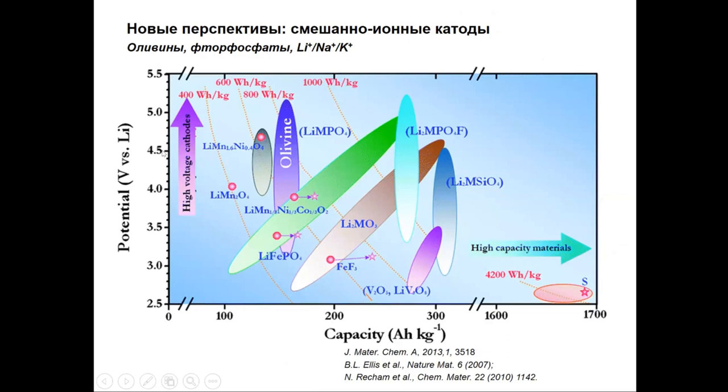And so there was a set of nice reviews quite some time ago that said, if you want to double the energy density and raise the operating voltage of the cathode, you should look at substituting more electronegative elements like oxygen and fluorine and phosphorus, so-called fluorophosphate type materials. There's of course some other ones, but they're less promising because the stability of the transition metal that provides the redox potential is very problematic.